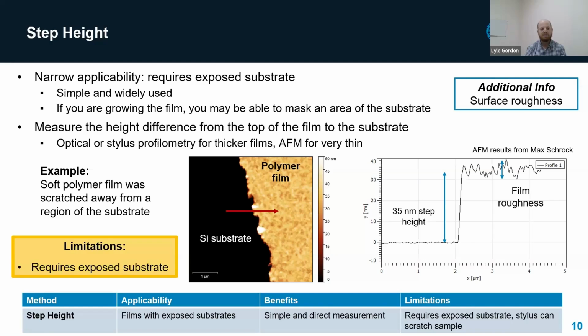So the main limitations here are if you don't want to damage or destroy your sample, you might not be able to access the substrate, or you have to scratch off your film. And then you get some additional information here. For example, you can see on the right of the profile that you can see and measure the film roughness. And so there's some extra information here that's accessible. And this is really easy and really widely used. Many people might be familiar with doing this when they're growing films to quickly check the film thickness.